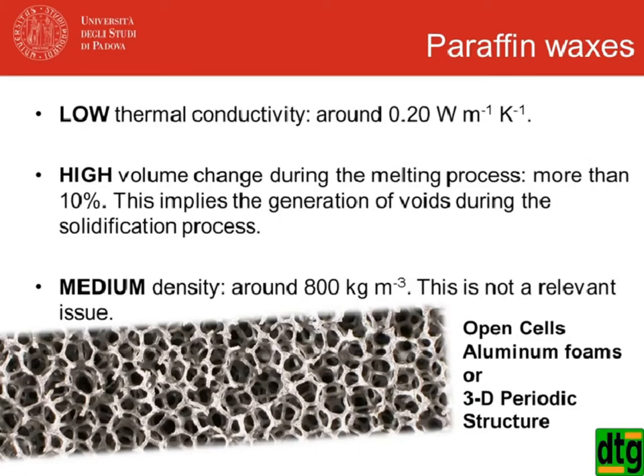The volume change implies that sometimes during the solidification process, voids might appear, and this has to be considered when you have high power applications, because sometimes it might happen that a void is located on a hot surface, on which you don't want a high temperature, for instance.